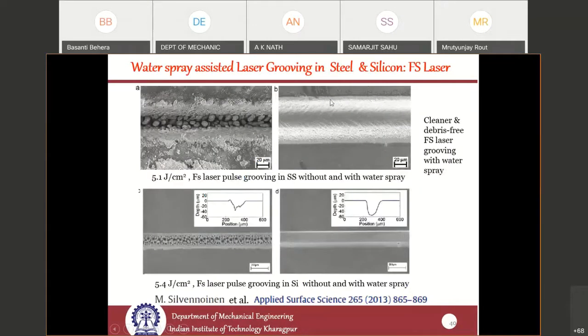Similarly, with the femtosecond laser, scribing and grooving has been done in silicon and steel. You can see that when you do it in air, this is the quality you get. When you do it with water jet assisted, you get very good quality. The water vapor generated because of the high intensity laser removes all the debris and melt recast, so there will be no melt recast and you get very good quality material removal.